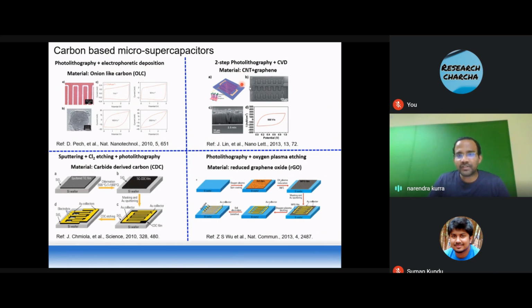And there were more efforts in making carbon nanotube graphene carpets using a two-step photolithography process followed by chemical vapor deposition. Such devices were employed in AC line filtering applications, which also have high rate capabilities because of the open porous structure. And similarly, there was a paper in Nature Communications in 2013 where a graphene oxide film was taken and reduced by a plasma reduction method at 700C, and then again photolithography was used to make graphene based micro supercapacitors.